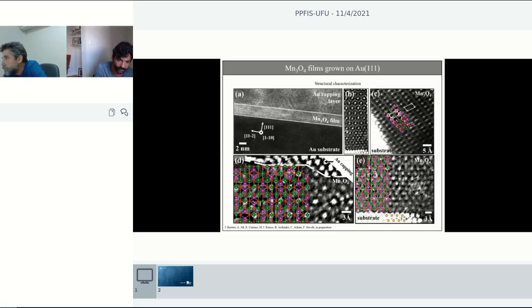So here in this model, I think it's useful to explain in a little more detail what we're seeing here. These red atoms that you see here are actually manganese in Mn3O4, which has a spinel structure where manganese +2 is sitting in a tetrahedral environment and manganese +3 is sitting in an octahedral environment. And that's why the green here is sitting on this site, that is an octahedral site, and this here is a tetrahedral site.